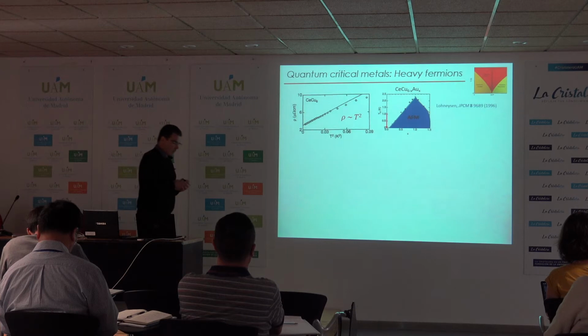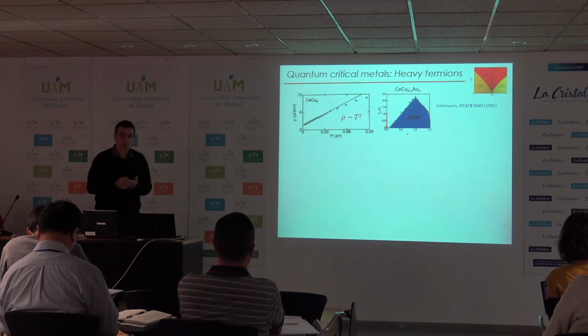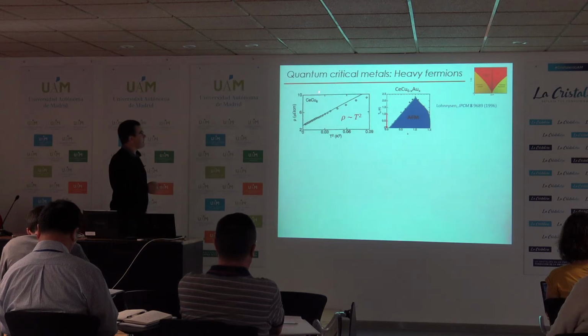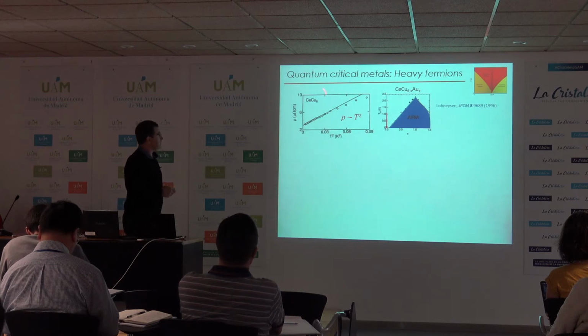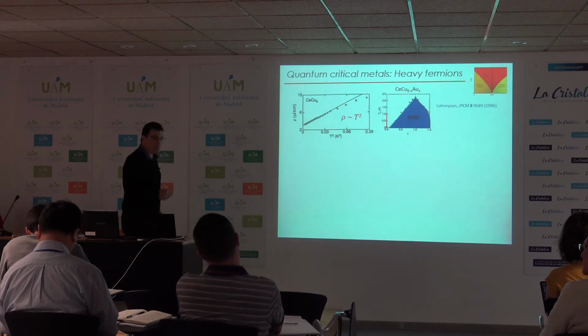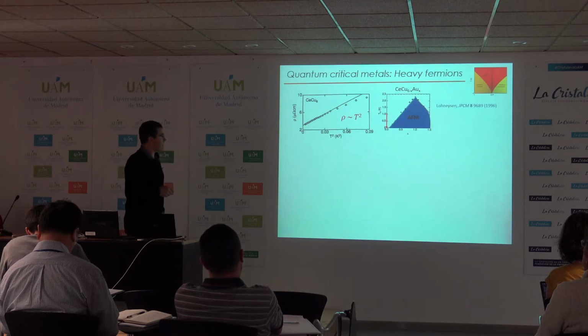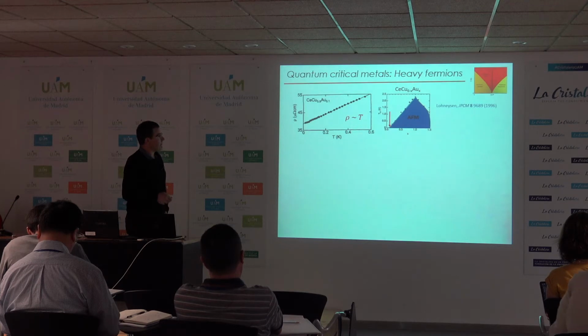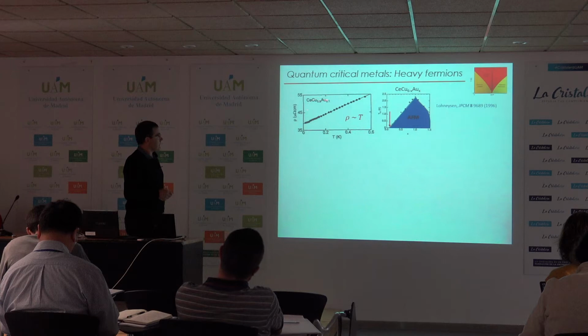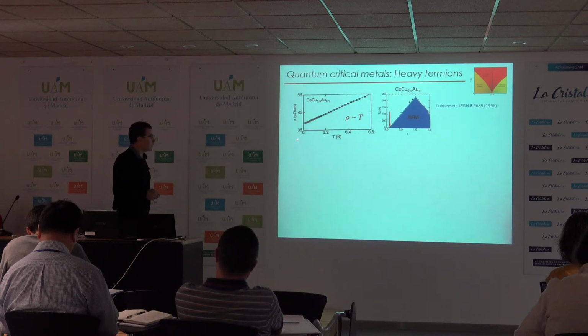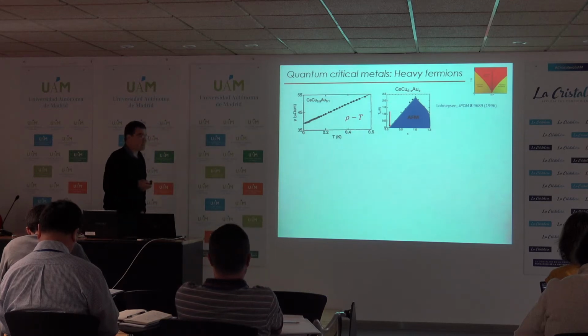So let me give you a few examples, from an experimentalist point of view, of what we observe close to the quantum critical point. Here I chose an example of the archetypal heavy fermion compound, cerium copper 6, which is a heavy fermion metal. The parent compound here is a metal. And here I show you the resistivity versus temperature plotted as T squared, where you see a hallmark of the Fermi liquid, meaning that the resistivity is T squared down to very low temperature. But as you can see in this phase diagram, as soon as you dope this compound with gold, at 10% you see an antiferromagnetic order that appears. And when you now measure the resistivity at 10%, you see that the resistivity remains linear down to very low temperature, as low as 10 millikelvin. So this is a signature, from a transport point of view, of the quantum critical point.